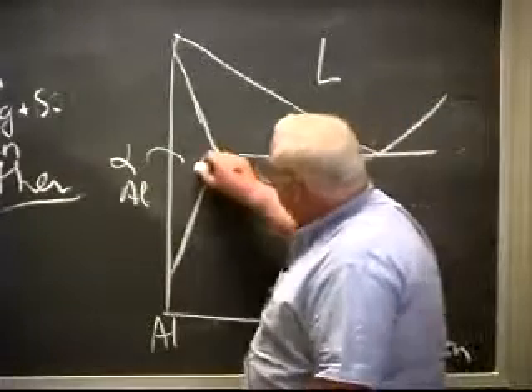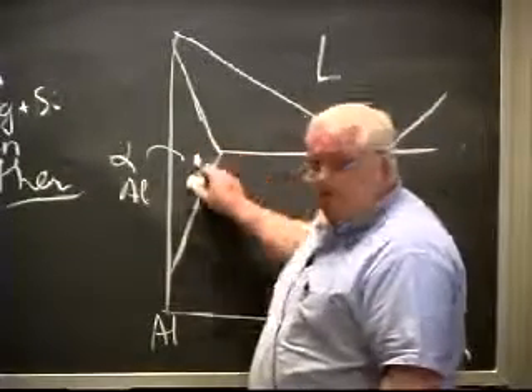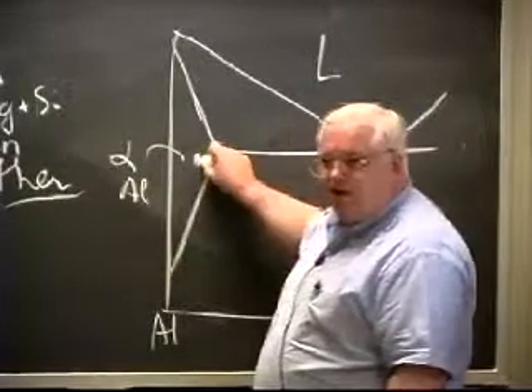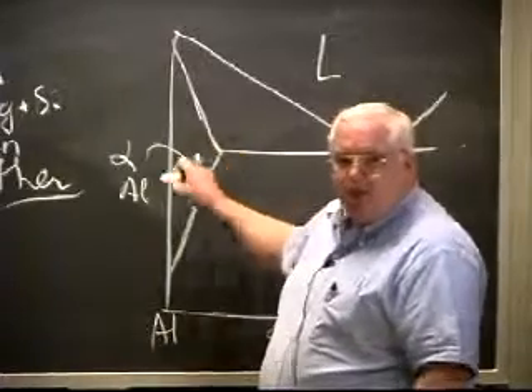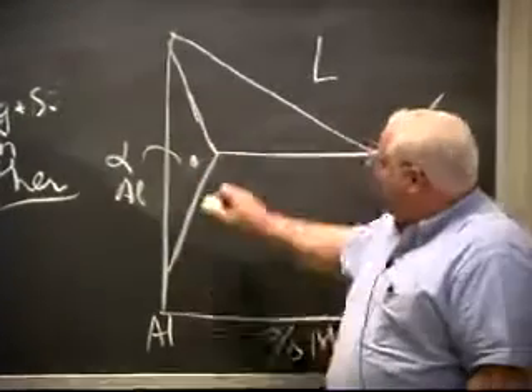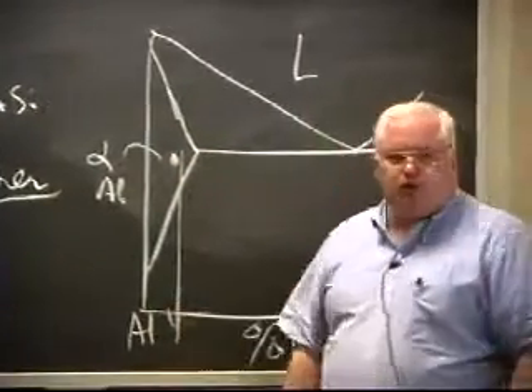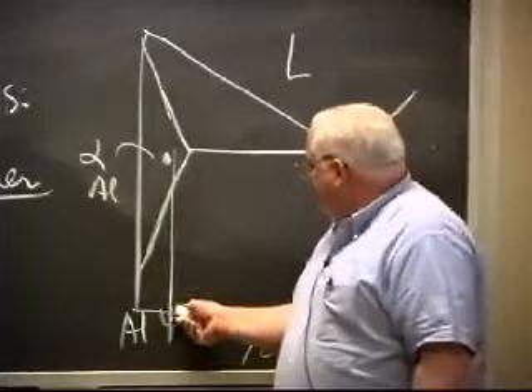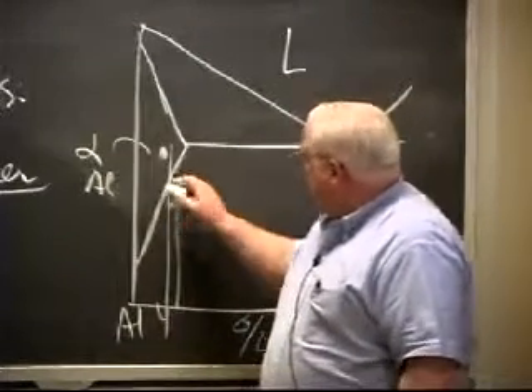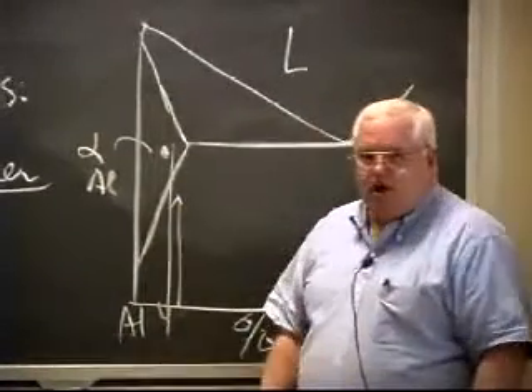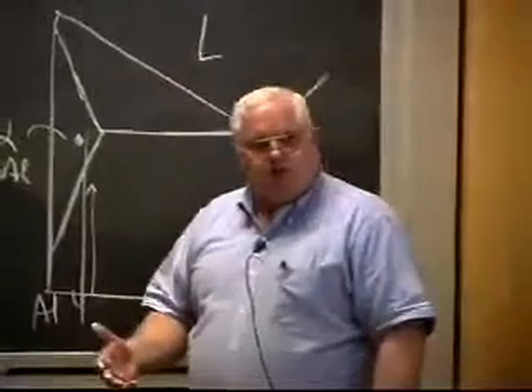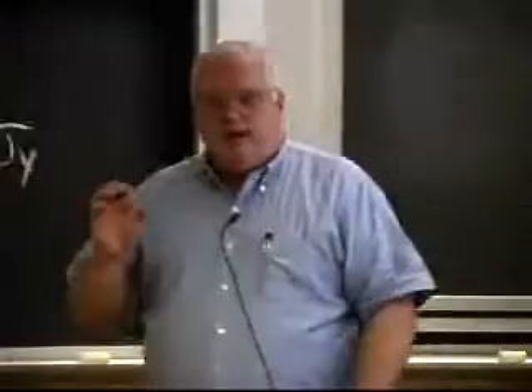And so if I heat the material up to this region, I'm above the solvus. I can dissolve all the magnesium or all the copper into the solution. I then quench it down to room temperature, and I heat it back up to some intermediate temperature below this solvus line, and I precipitate out little particles of these intermetallics. That's the heat treatment I do on the aluminum alloys.